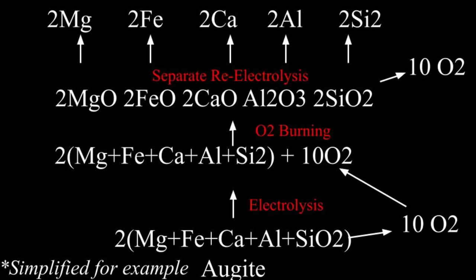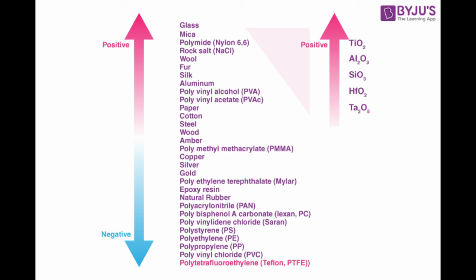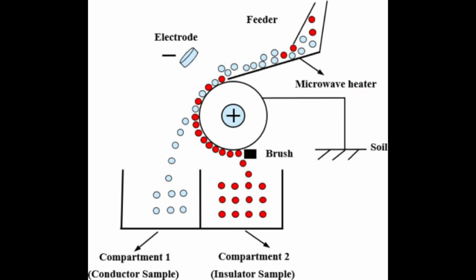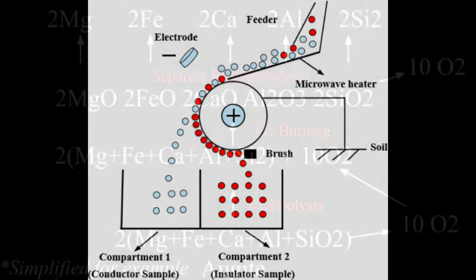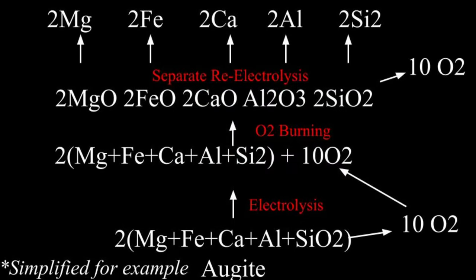Once they are reformed into oxides, they could then be separated individually through triboelectric beneficiation. This process uses static electricity to deposit electrodes onto a material. Materials with a higher affinity for electrons gain more electrons, and so will be more negative than materials with lower electron affinity. Electron affinity is dependent on the chemical composition of the particle surface, and will result in substantial differential charging of materials in a mixture of discrete particles of different composition. Once you've separated all the oxides from each other, you can then re-electrolyze them individually, removing the oxygen.